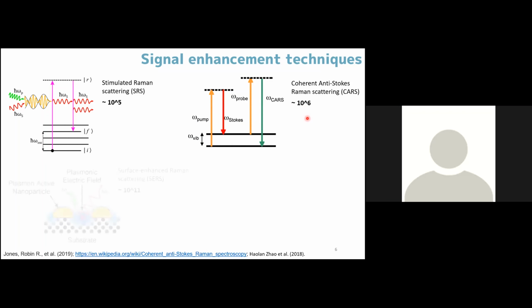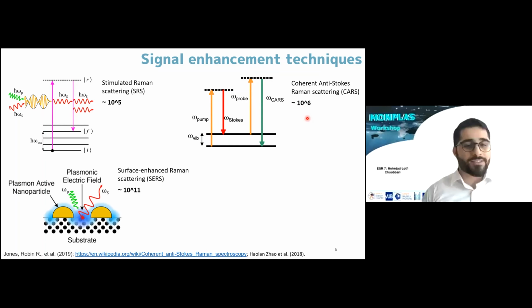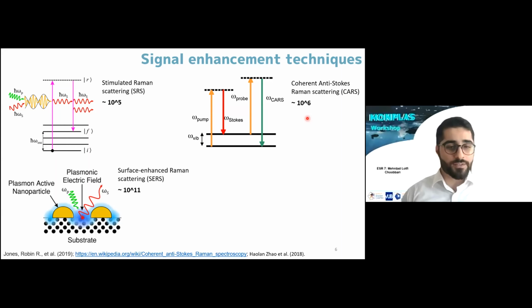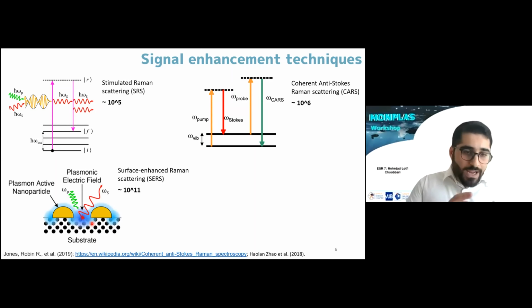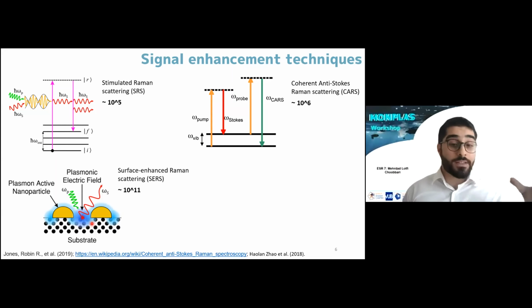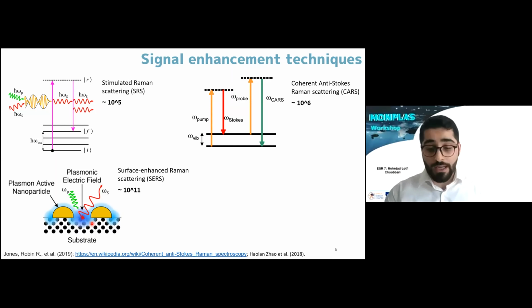Raman spectroscopy. The next method, which is very popular for enhancing the Raman signal, is called surface enhanced Raman scattering, or SERS, in which we take advantage of surface plasmon resonance to enhance the local electromagnetic field in regions typically called hotspots. And these high electromagnetic fields can in turn intensify the light matter interaction and therefore increase the Raman signal up to 10 to the power 11 in comparison to the signal obtained by conventional Raman scattering.